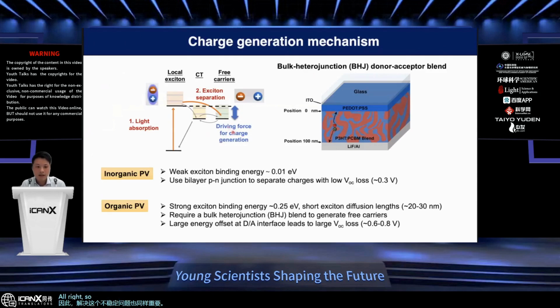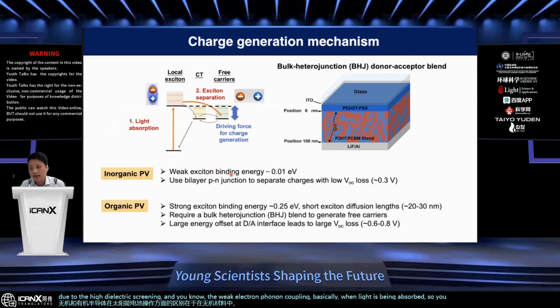All right, so the difference between inorganic and organic semiconductors in terms of solar cell operation is that in an inorganic material, due to the high dielectric screening and the weak electron-phonon coupling, when light is being absorbed, so you promote an electron from the ground state to the excited state, the electron can separate from the hole left in the valence band relatively easily. What that really means is that an exciton is the electron hole pair that you generate upon photoexcitation. And this exciton in inorganic materials has rather low binding energy. So they can very readily separate as long as you give them some thermal energy.